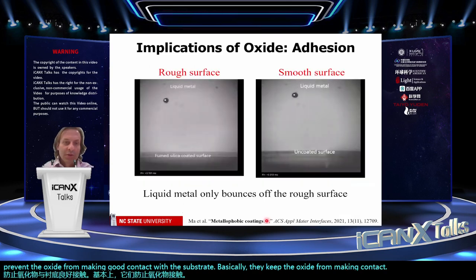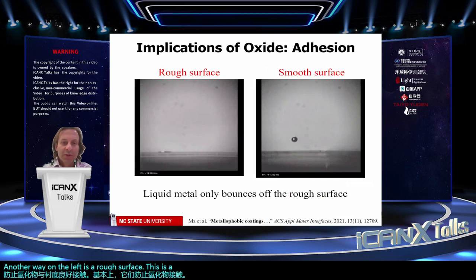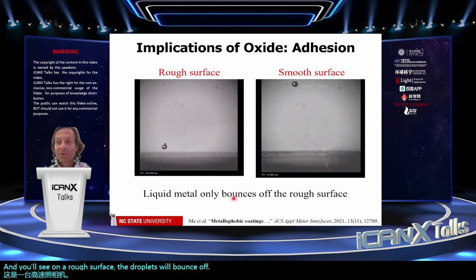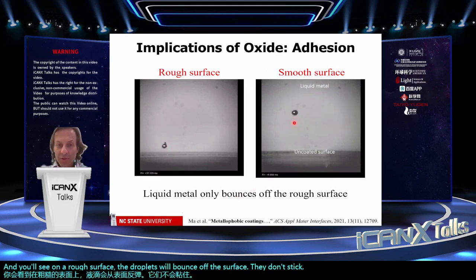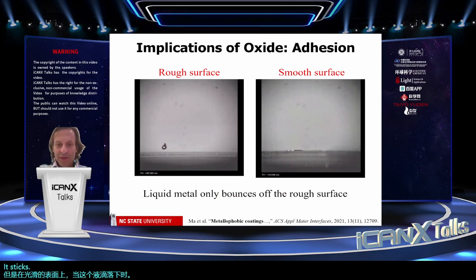So to show you this just in another way, on the left is a rough surface. This is a smooth surface. This is a high-speed camera. And you'll see on a rough surface, the droplets will bounce off the surface. They don't stick. But on the smooth surface, when this droplet comes down, it hits the surface, it flattens, and it sticks.